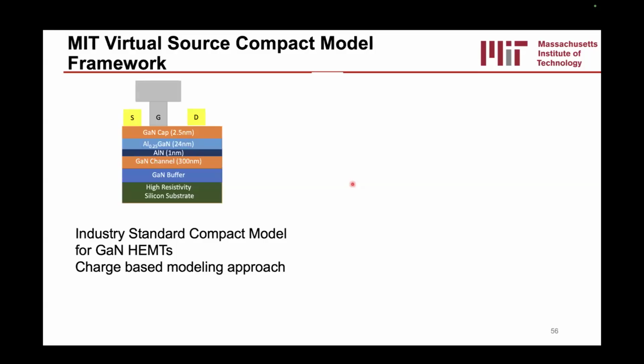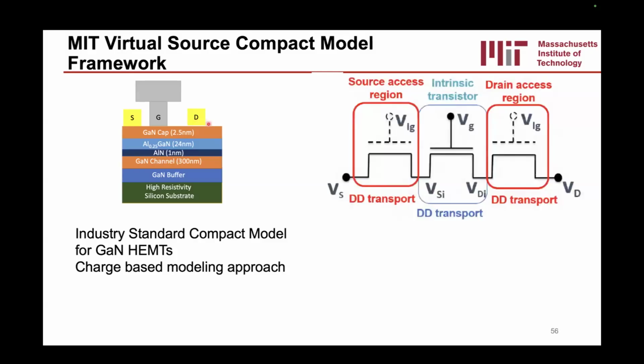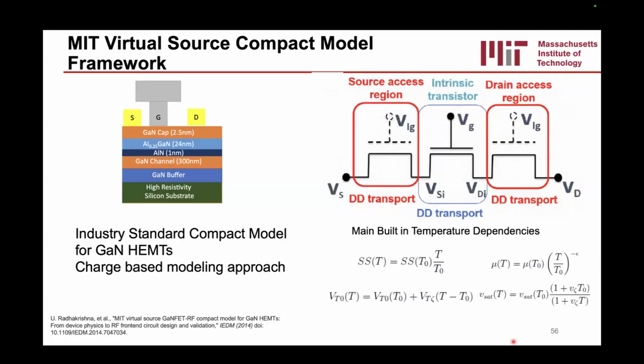What we did for modeling these devices was use the MIT Virtual Source compact modeling framework, which basically models almost any GaN transistor using a kind of 3 transistor model, one for the source and drain access regions, as well as the intrinsic transistor. And it's a charge-based model, and it has a few temperature dependencies, including the series resistance, the mobility, the threshold voltage, and the saturation.